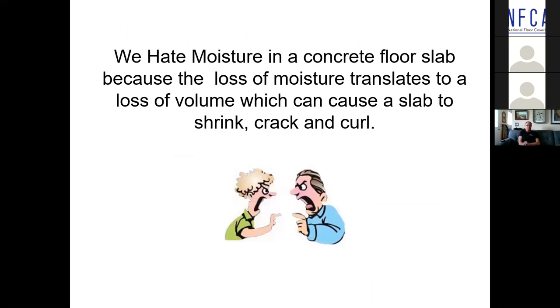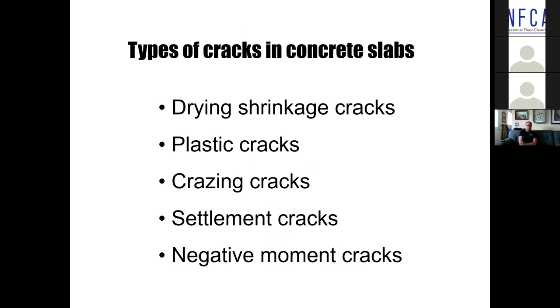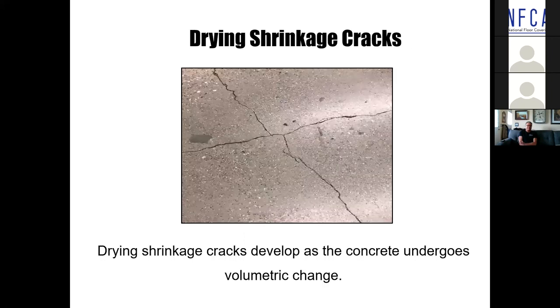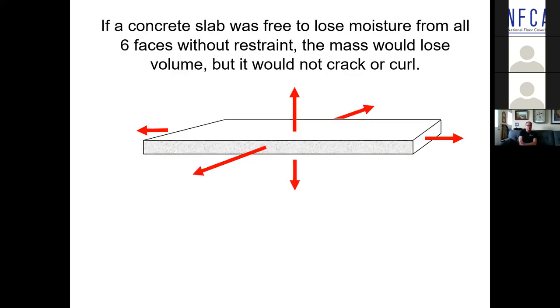So we hate moisture in a concrete slab because the loss of moisture, as we talked about earlier, can create a volumetric change. And volumetric change can result in drying shrinkage cracks, plastic cracks, crazing cracks, settlement cracks, negative moment cracks. Drying shrinkage, just simply the loss of moisture, if there's no provision for it, the loss of volume creates a volumetric change, and the friction of the deck or the friction of the ground can cause the concrete to crack.